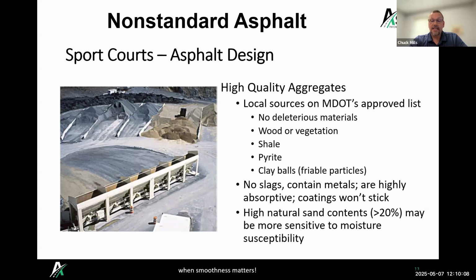High natural sand contents may be more sensitive to moisture susceptibility. Typically, you want to limit the natural sands to under 20% in your mix designs. And many producers, I know from here in Michigan anyway, a lot of times when they're doing a sports court, they have a special mix design where they use 100% limestone. That makes sure that they don't have those deleterious materials you sometimes get if you use natural aggregates, like gravels and different things like that.